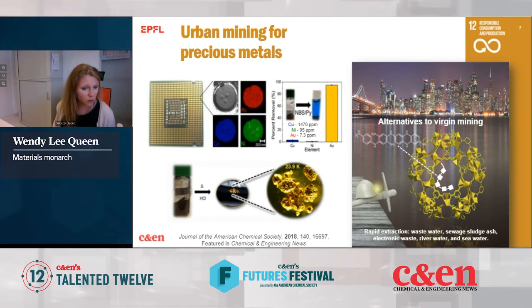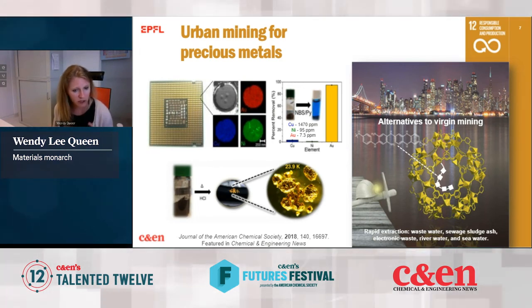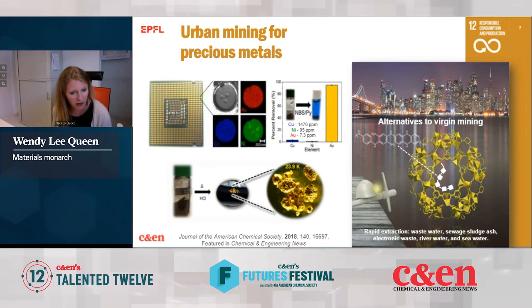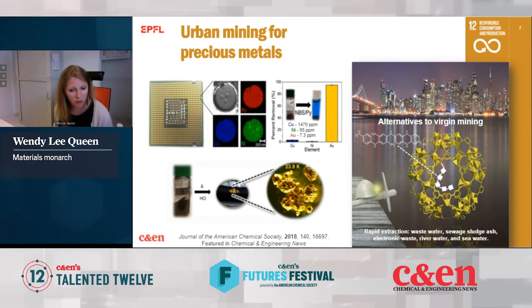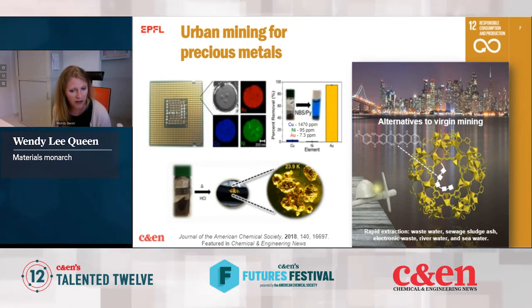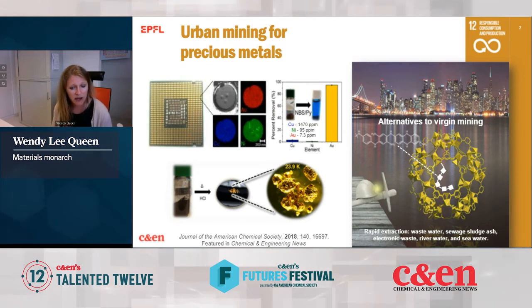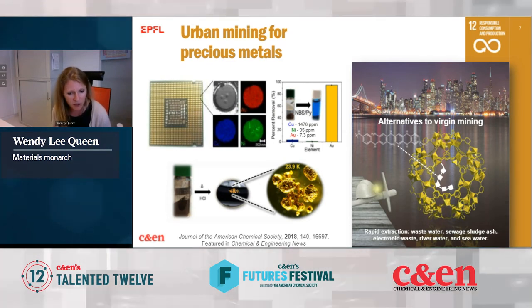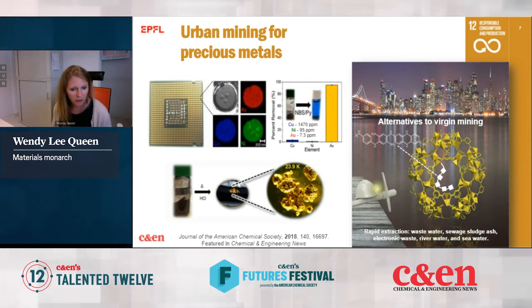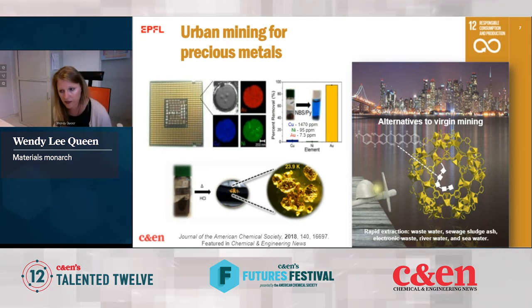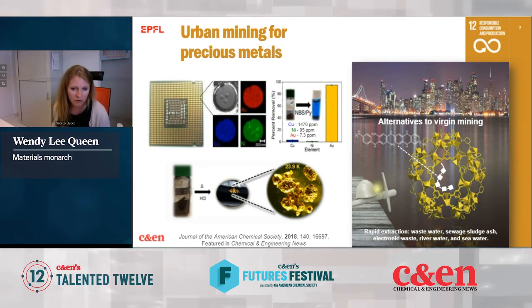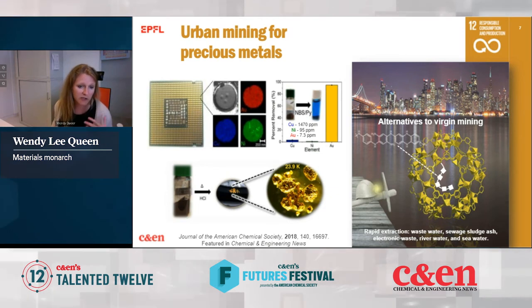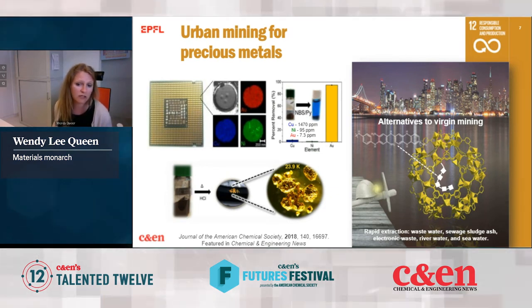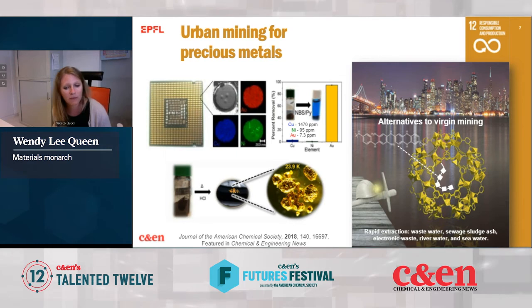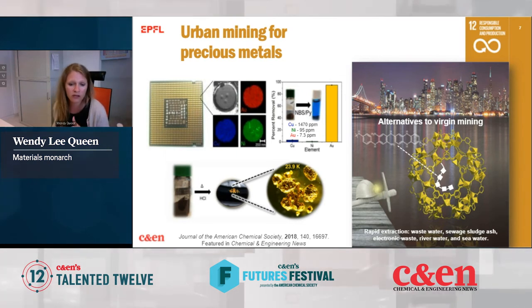And what we essentially do once it's full, it's reached its capacity, which is about 1 gram of gold per gram of composite. We then destroy that sponge, and what we're left with is 23.9 karat gold on the back end. This is the highest purity reported to date for such an extraction process, and this is directly related to the material's high selectivity, as I mentioned before. So if you look at the extraction, it's a little over 600 times more selective for gold than it is for copper.